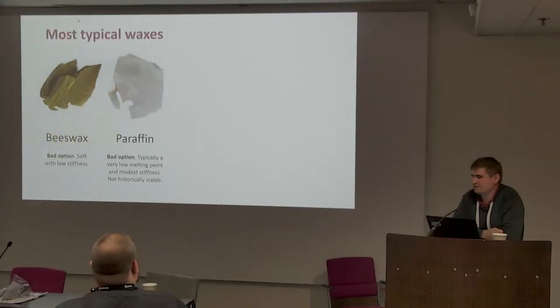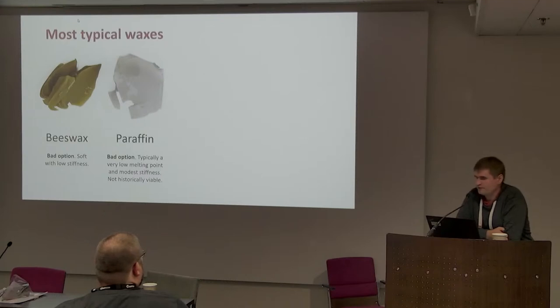It's quite soft, not as soft as beeswax, and it has modest stiffness. And most critically, you have some high melt point paraffin waxes, but most of the paraffin waxes you get are very low melt point. So even in Finnish summer, which is not exceptionally hot, your leather armor will melt in the direct sunlight.